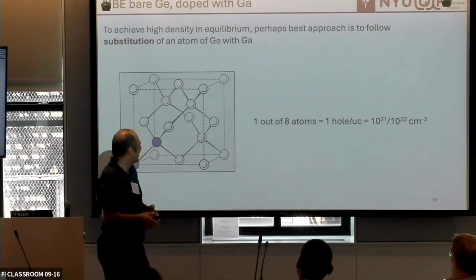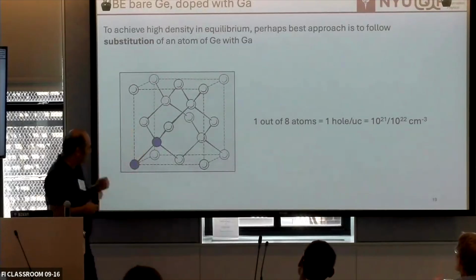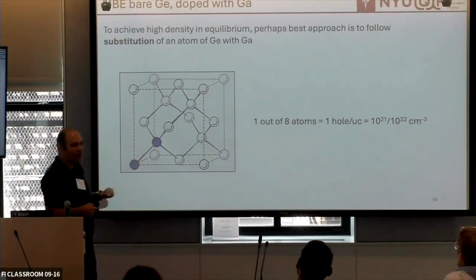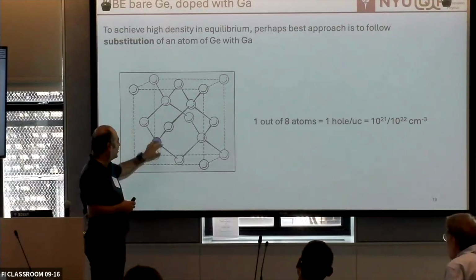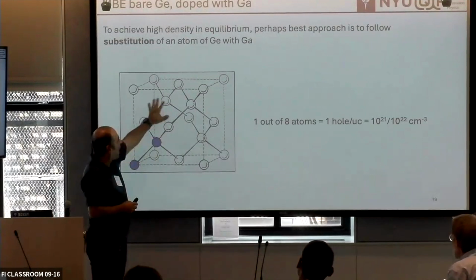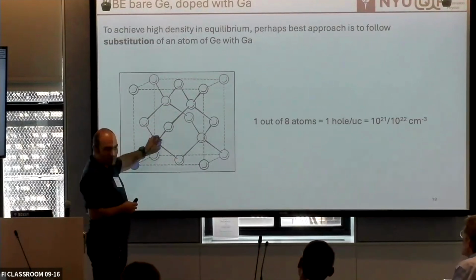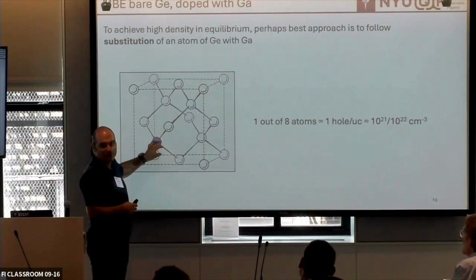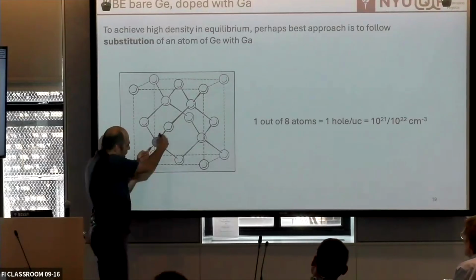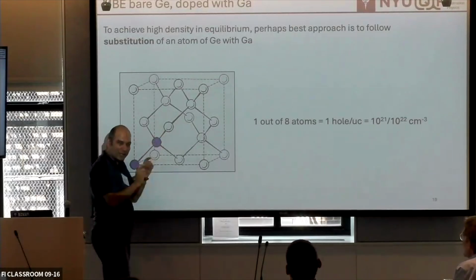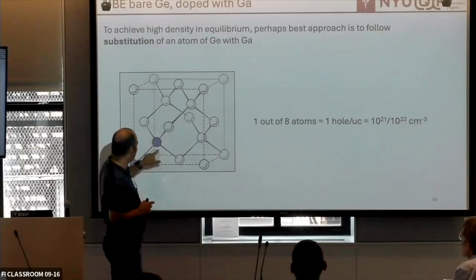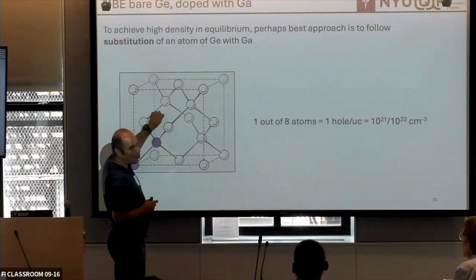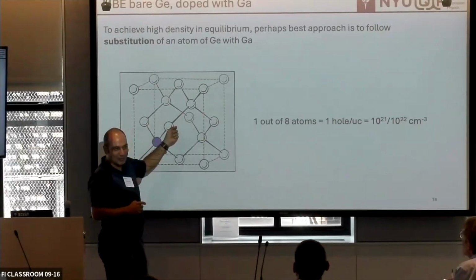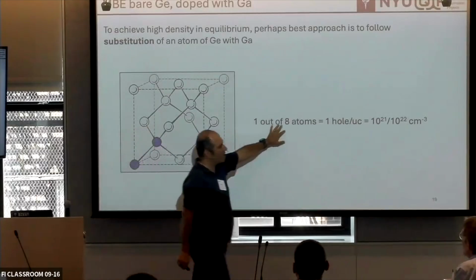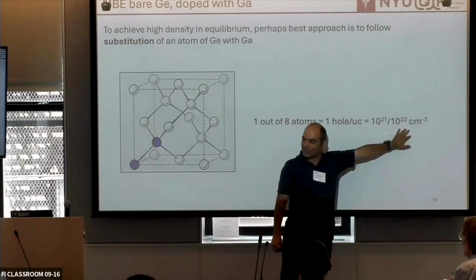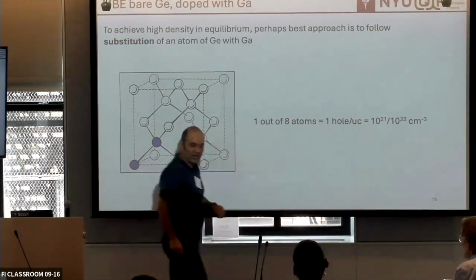Maybe there's another way. And then another very smart postdoc said, why not we try to grow this in a regime that basically in the lattice of germanium, we just replace one with a gallium. So that way, yeah, this bond is distorted a little bit, but gallium and germanium, actually the mass are very similar. Then we will have an extra hole per unit cell. So now if you calculate, you can easily reach these kind of densities, if you can basically do that.